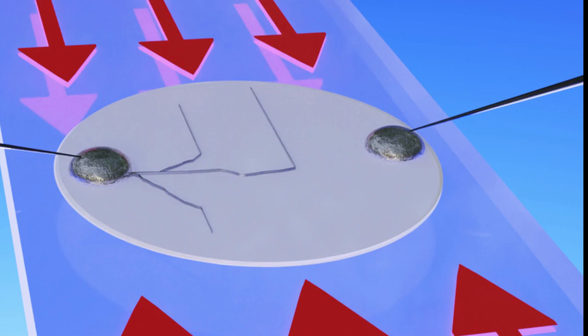And the amount of pressure needed is not extreme. The experiment showed that pressures of 150 to 200 megapascals were sufficient to stop the dendrites from crossing the electrolyte. The required pressure is commensurate with stresses that are commonly induced in commercial film growth processes and many other manufacturing processes, so should not be difficult to implement in practice.